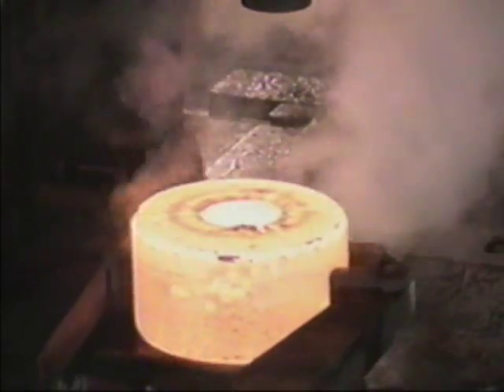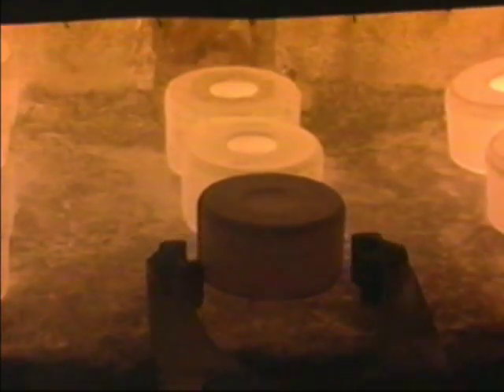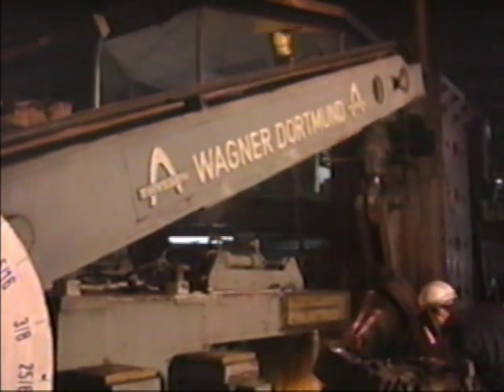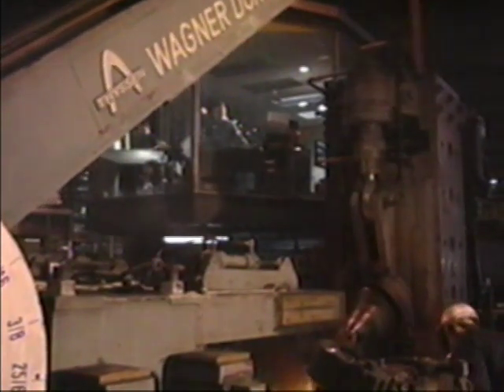Because of the heat loss during this process, the blank is loaded into a reheat furnace to return it to forging temperature. The blanking and rolling of the ring are controlled from a control room high above the shop floor. The reheated blank is loaded onto a 100-ton radial, 80-ton axial ring mill, a sophisticated piece of equipment designed specifically for the purpose of manufacturing seamless rolled ring forgings.